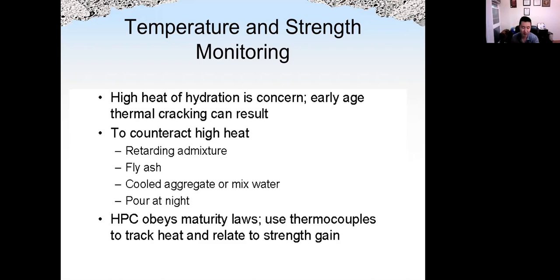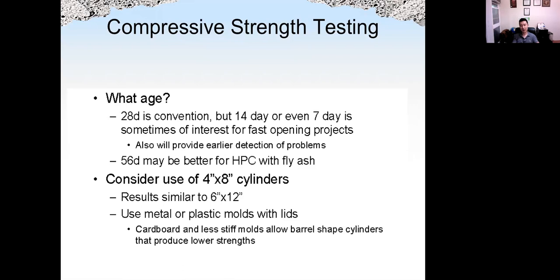And high performance concrete will obey maturity laws. So if we monitor the temperature change using thermocouples to track the heat, we can relate that to the strength gain. And here you can talk about how and when we test the strength of concrete. Normally we check the strength at 28 days. But because we may use silica fume or retarder or fly ash, 14 days or even 7 days sometimes is also required. If we use fly ash, we may check the strength at 2 months or even 3 months because hydration will be slower.